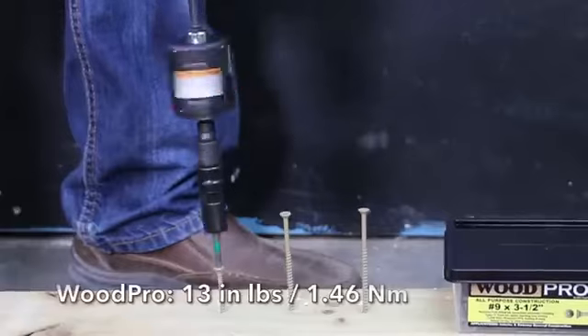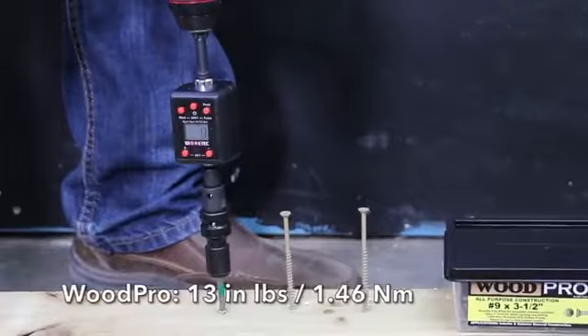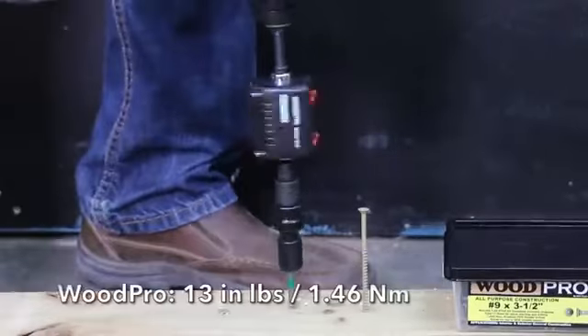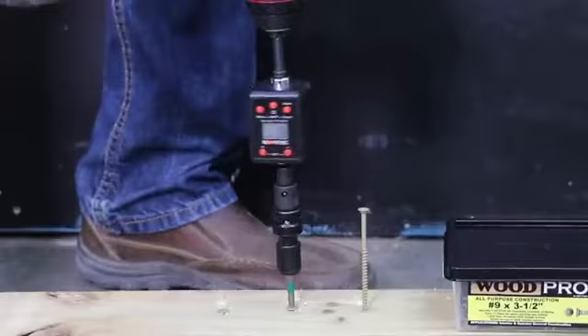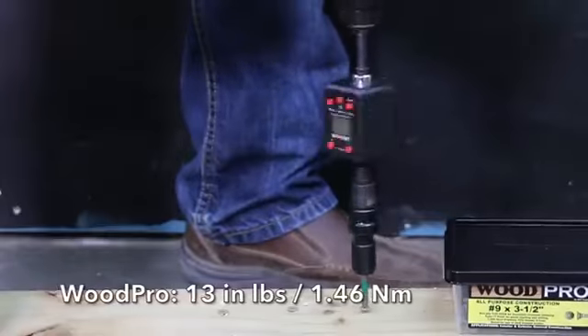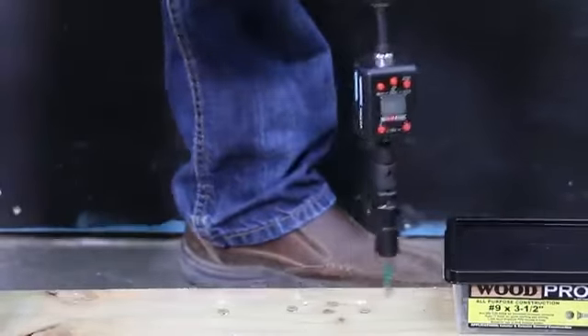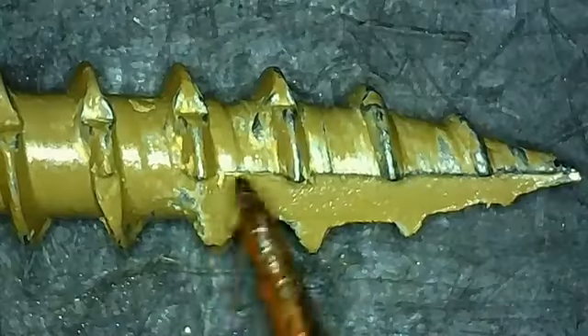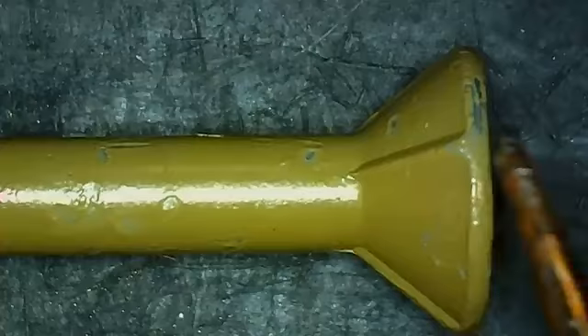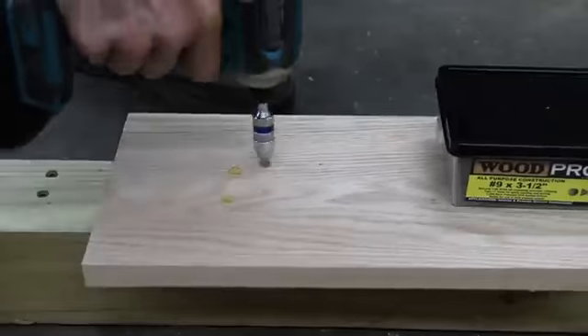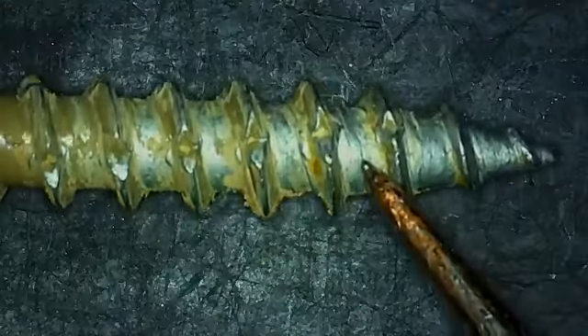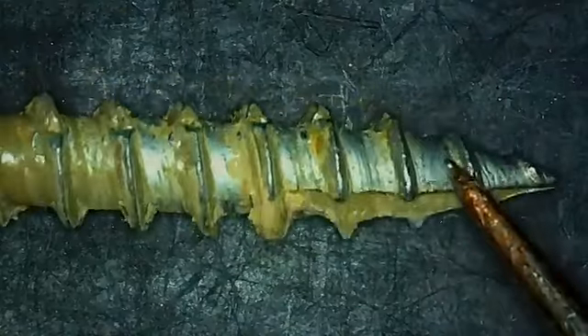The WoodPro is a number 9 screw and it took less torque than the Deckmate at 13 inch-pounds. The second screw was the same as the first at 13 inch-pounds. The third screw was the same as the first two at 13 inch-pounds, so very consistent results from the WoodPro. The WoodPro's coating seems to have held up better than the Deckmate, but there's metal showing in several areas. Drilling through the oak really caused a lot of damage to the coating on the WoodPro, but it does seem to have held up slightly better than the Deckmate.